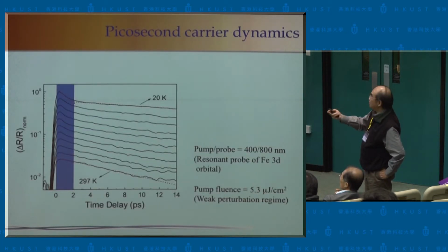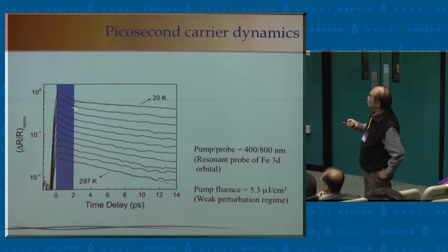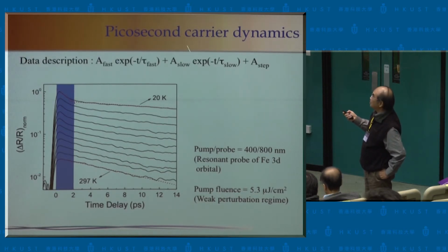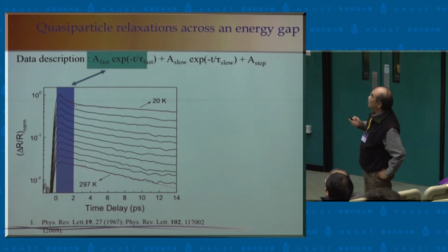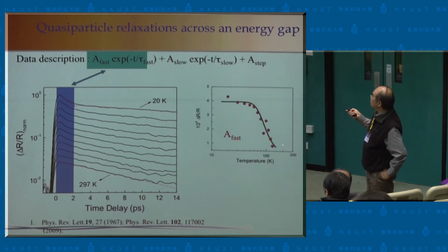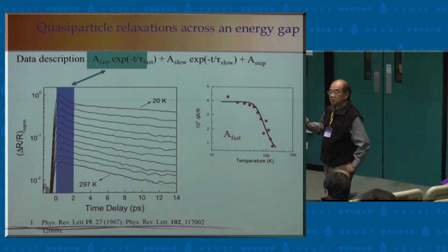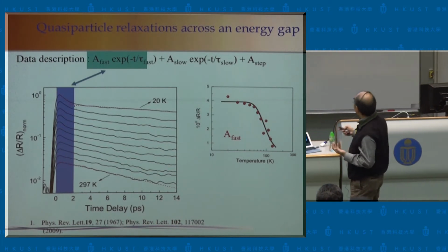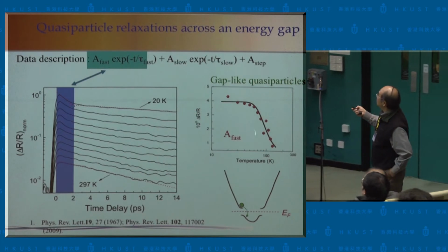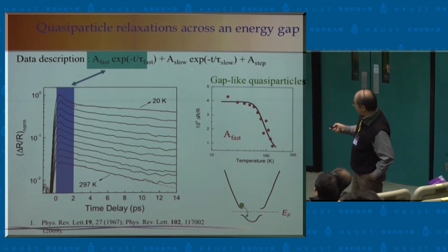And then we look at the low temperature signal in order to find out the carrier dynamics. We see that when we cool down, the whole spectrum changes drastically in the very short time domain, and this can be described by a simple formula. By analyzing the data for the fast relaxation, it shows that there is a very sharp rise in this coefficient. This strongly suggests there's some kind of gap opening here, in the absorption. So this is the temperature around 100 K, where the spectral weight change is associated with it.